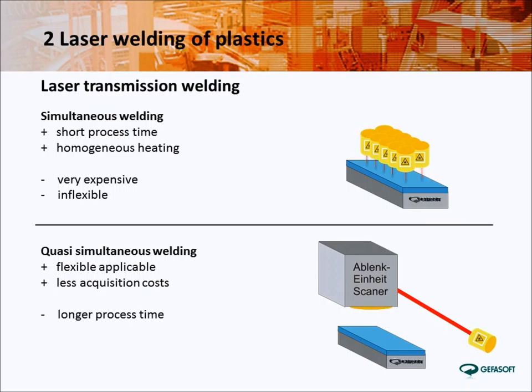A very popular process in the past is the simultaneous welding. The welding contour of the product is lit from many laser sources simultaneously. Typically, this is realized by many optical fibers which are placed directly above along the welding contour. Again, this process can achieve especially short process times because of the homogeneous and simultaneous heating of the welding area. The implementation of such welding tools is quite complex and is both maintenance and cost intensive.